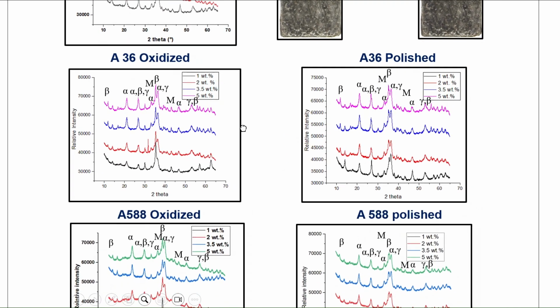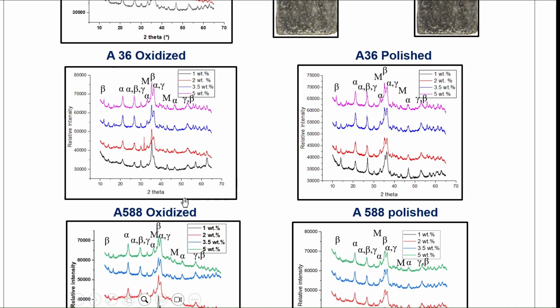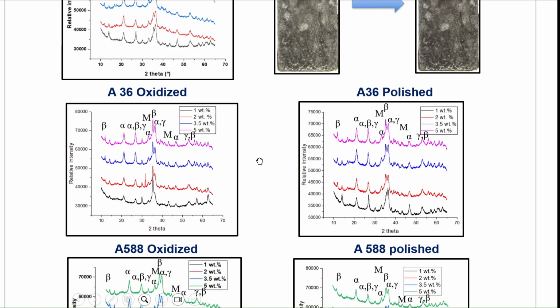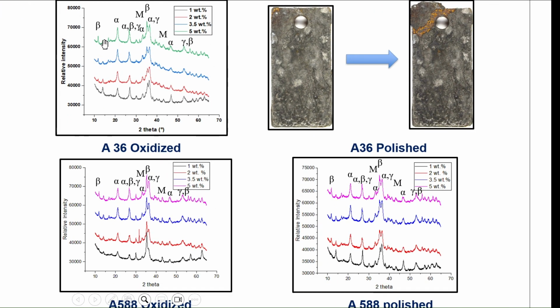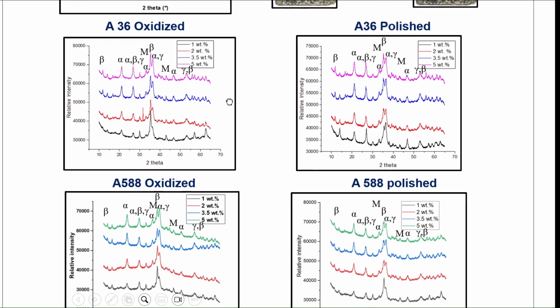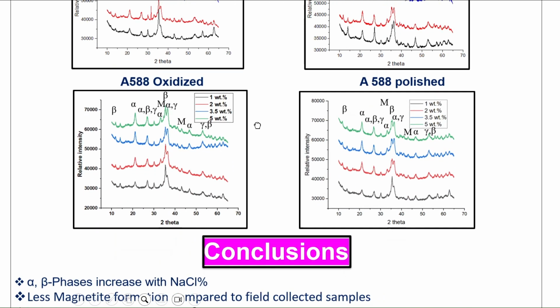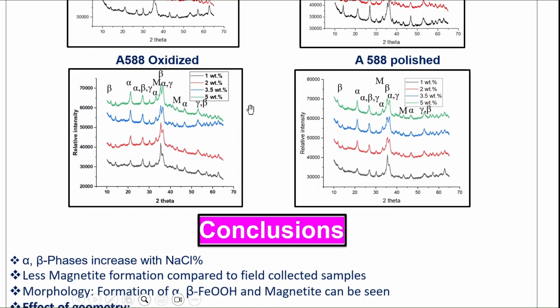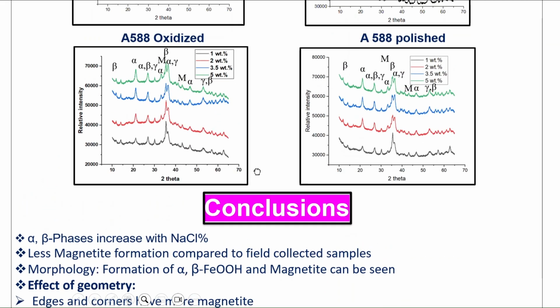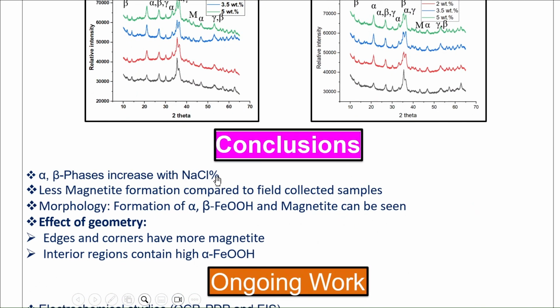And we can see similar performance in A36 and A588, that beta will increase with the salt concentration as alpha does. But the beta peak is really high in the case of A7, less in A36, and very little in A588. So coming to the conclusions, we can say that alpha and beta phases increase with NaCl percentage,